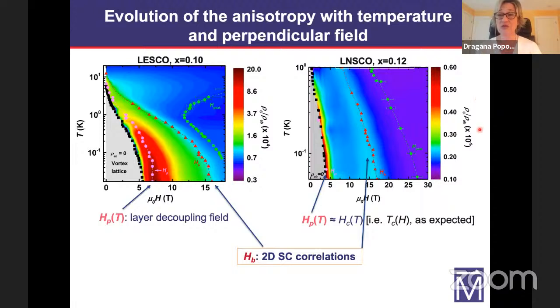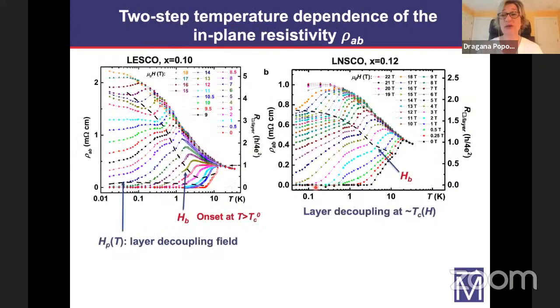So in LNSCO, which is at 1/8 doping, the situation is qualitatively the same. You can see the same enhancement. You can see this light blue band here, the enhancement of the anisotropy as the field is reduced from the normal state below the upper critical field. The only difference here is that this decoupling field basically coincides with the Tc, because this system is already at 1/8, it's fully frustrated, and this is precisely what is expected within this pair density wave picture. So it is also helpful, I think, to compare the behavior of the anisotropy ratio to the temperature dependence of the in-plane resistivity for different fields.